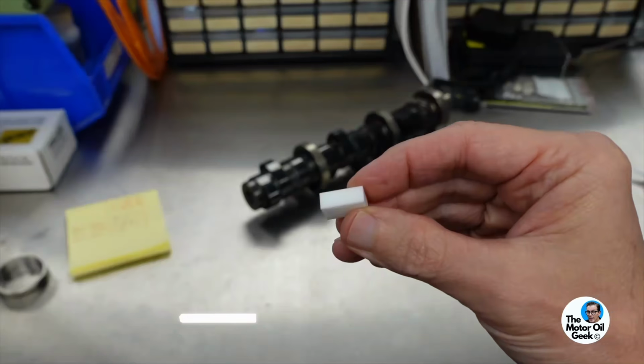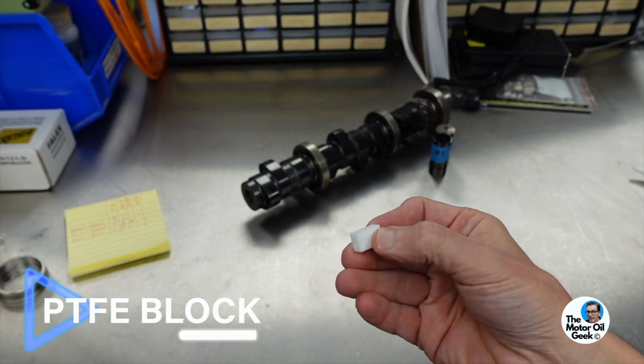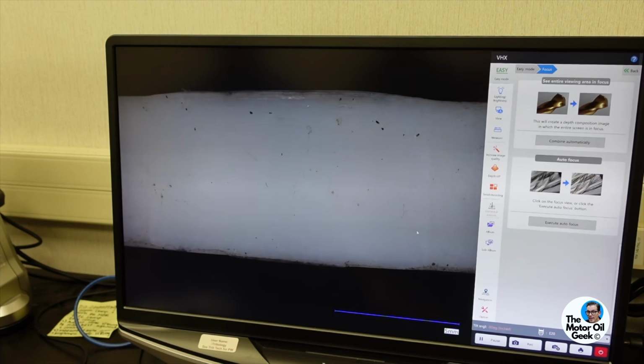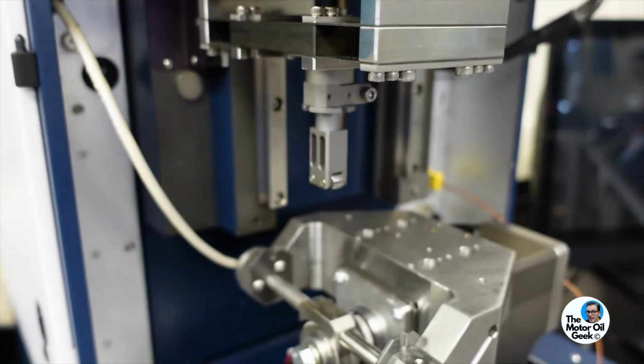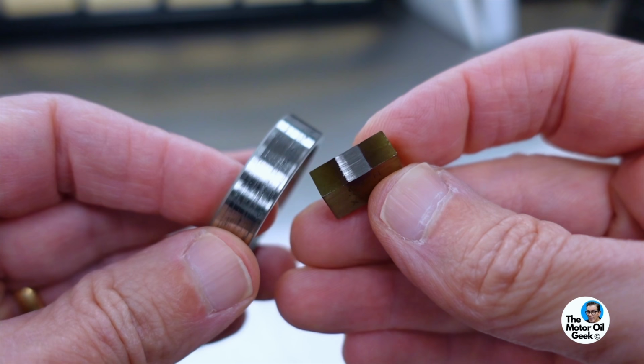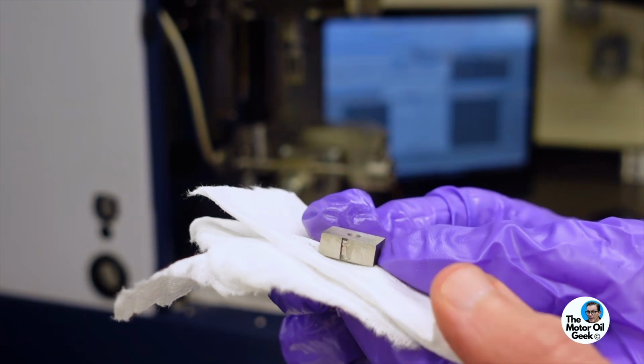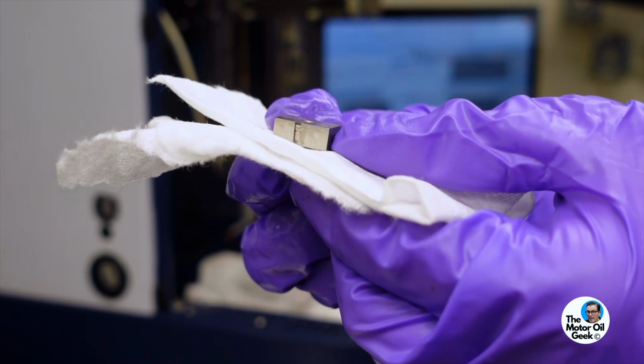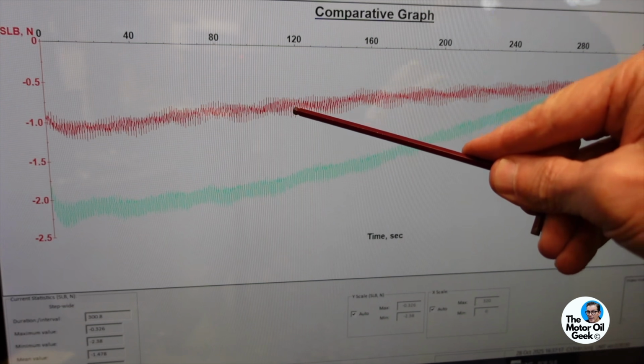So one of the things that we've done is we've actually run, instead of a steel block on a steel ring, a PTFE block on a steel ring in this test rig here. And what happens is the PTFE does wear a lot faster because it's soft, but it actually transfers across to the steel, so you end up running PTFE on PTFE. So the friction goes down. Just to show that, we also then took that PTFE block out and put a steel one in. So at this point we have a fresh steel block running on a steel ring that's got PTFE transferred onto it. And we ran that as well. And as you can see, the friction slowly comes back up to steel on steel values because that PTFE wears